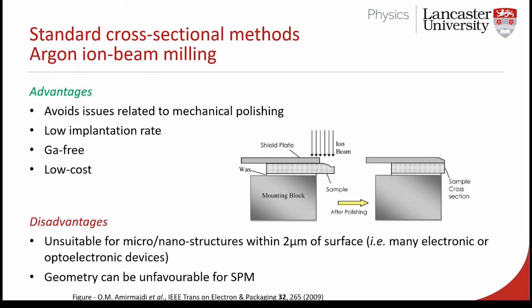What Alex and other colleagues in the department developed was this modification to what is a relatively cheap, relatively quick and benign argon ion beam milling technique. So this is typically used in the way you can see on the screen now for quite sharp cuts through a material. It's very good. It has a low implantation rate. It doesn't contaminate the surface, particularly if the surface is protected on the cut. But the disadvantage for this is that it's not great for accessing buried information for scanning probe microscopy.